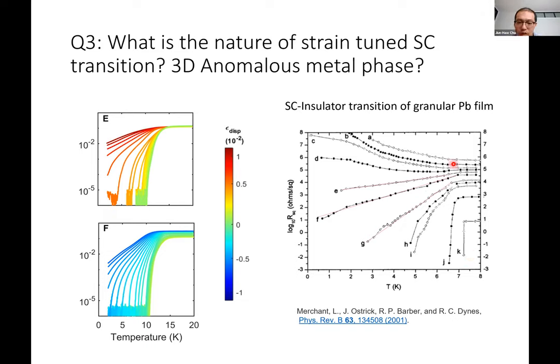And then in between this transition, they also see the log of resistance change linearly as a function of temperature. So perhaps that also implies that we have some strong intrinsic electronic inhomogeneity in the system that just behaves like superconducting islands that don't couple to each other. So I think that's a very interesting direction to explore.